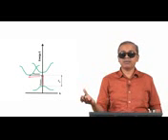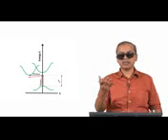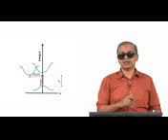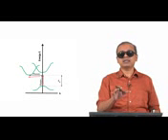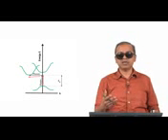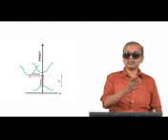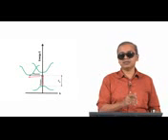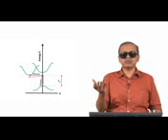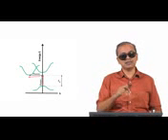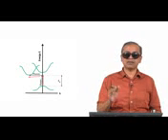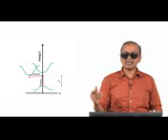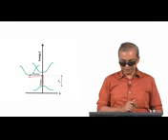So as we look at photovoltaic materials, we will recognize which is a direct band gap semiconductor, which is an indirect band gap semiconductor. Indirect band gap semiconductors are being used for solar applications, but they have limitation. This is the limitation that is there in the background that we should be aware of. And so when some other materials are explored and greater emphasis is placed on some other materials, this is one of the reasons why that emphasis is being placed, even though you may see that band gaps don't look terribly different, but inside this there is this detail that one is direct band gap, the other is indirect band gap. So better chance that it will absorb the solar radiation and do the transition. There is a lesser chance that it will absorb the radiation and do the transition.